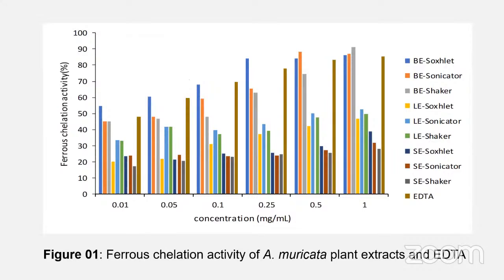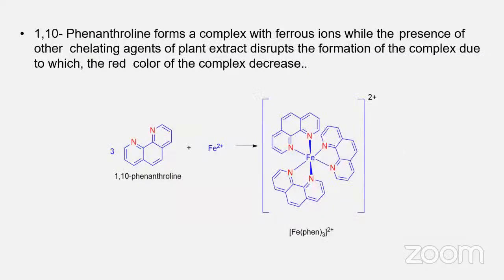So according to the results, we can see the activity depends on the concentration and the plant material, and it changes slightly with the extraction method. Every time, the bark has shown promising activity higher than EDTA, and the seeds gave weak activity. 1,10-phenanthroline forms a complex with ferrous ions, while other chelating agents in plant extracts inhibit the formation of that complex. That is why we observed a decrease in the intensity of the red color of that complex. Then we can calculate the inhibition percentage as the ferrous chelation activity using the absorbance value.